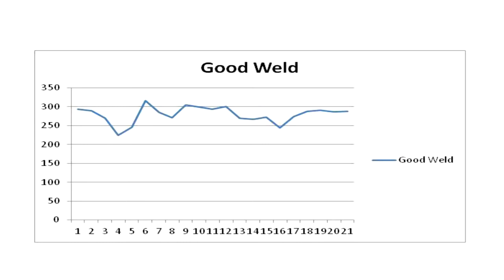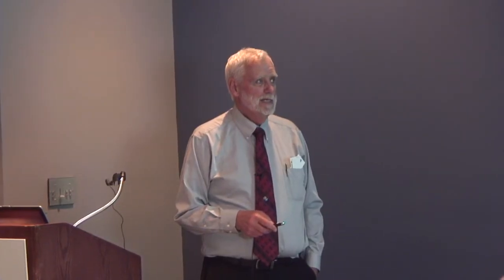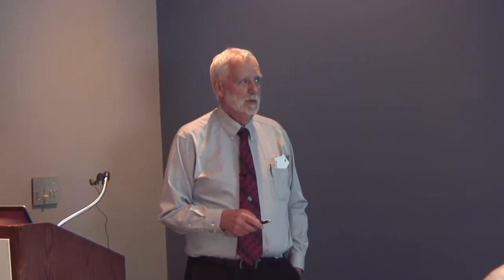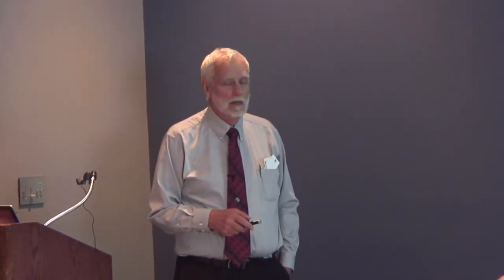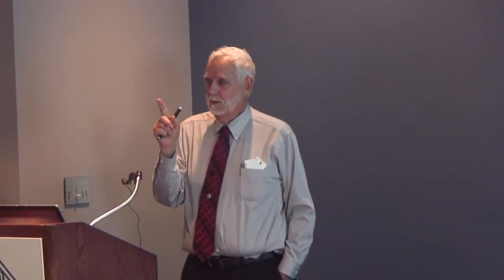The good weld, this is really good here. Now, the weld shaped like this. Well, the hardness traverse was right through the center, 1/4 inch down from the top. And you notice that this is the base metal hardnesses, and they were a millimeter apart. And there was about 18 of them, I think. So this was the center of the weld, right here. This is the base metal. The base metal got a little dip for the heat affected zone, and then the weld metal was the same hardness as the base metal. That's what it got quenched just fast enough to cool, to harden a little bit, but it wasn't too hot to anneal the material.